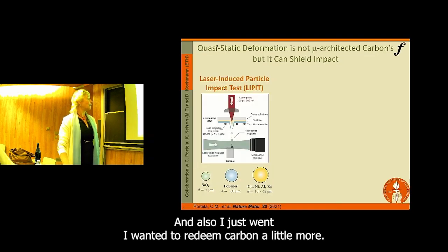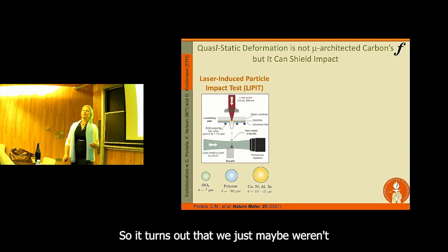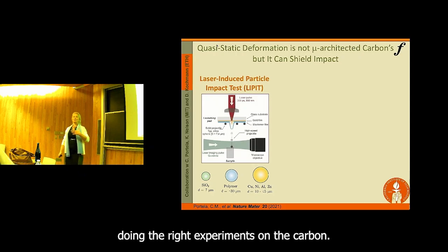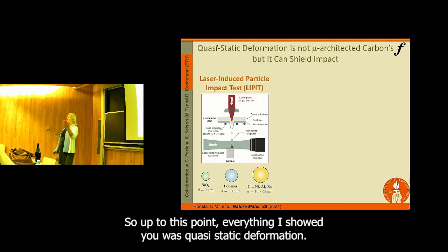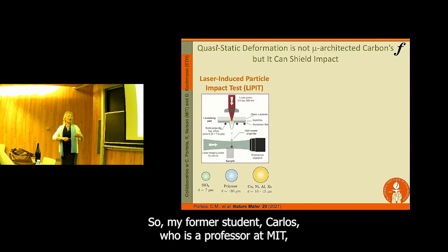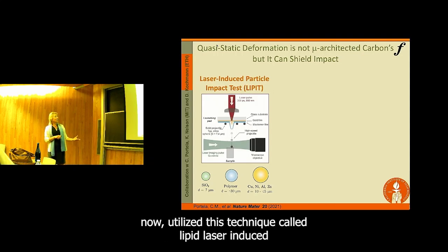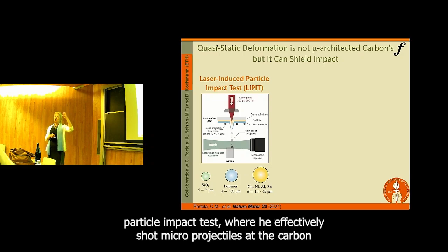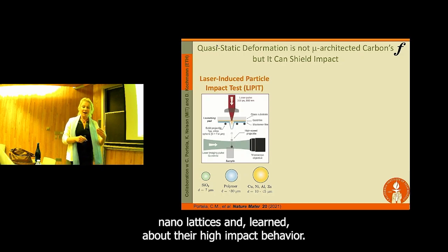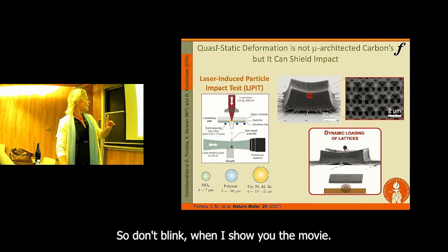And also, I just wanted to redeem carbon a little more. So it turns out that we just maybe weren't doing the right experiment on the carbon. Up to this point, everything I showed you was quasi-static deformation. So my former student, Carlos, who is a professor at MIT, now utilized this technique called LIPIT, laser-induced particle impact test, where he effectively shot microprojectiles at the carbon nanolattices and learned about their high-impact behavior. So don't blink when I show you the movie.